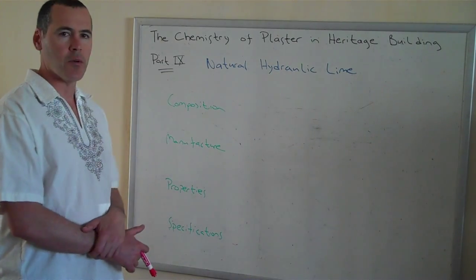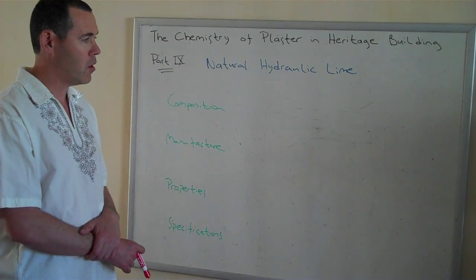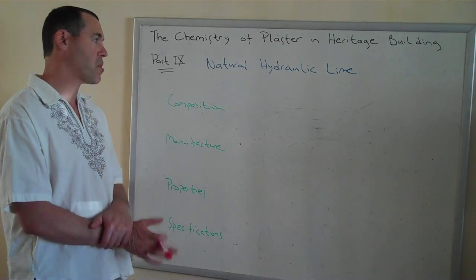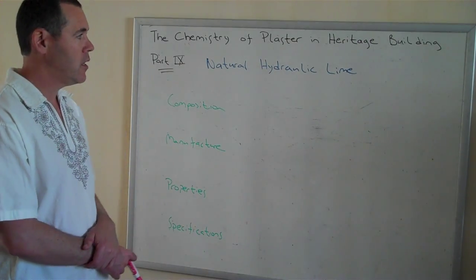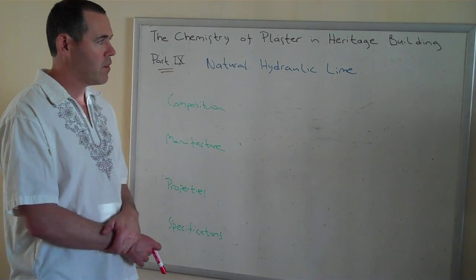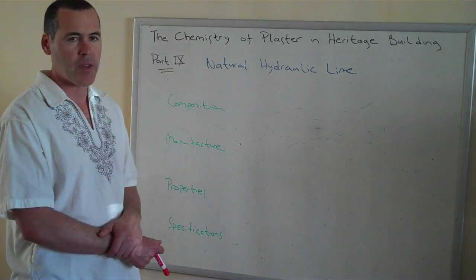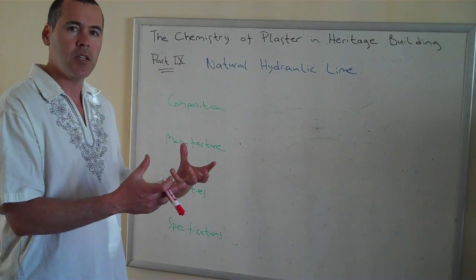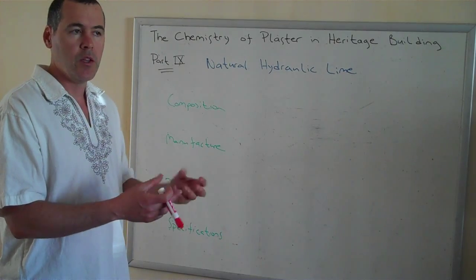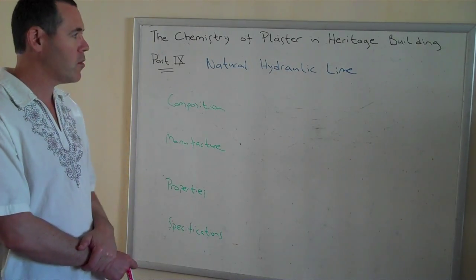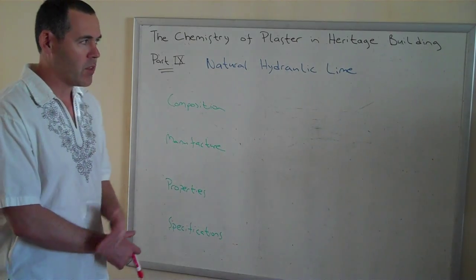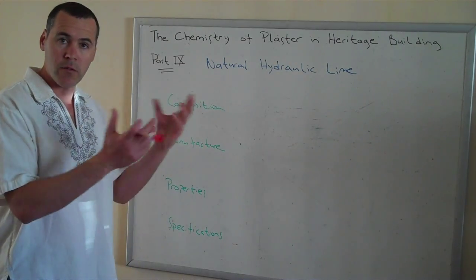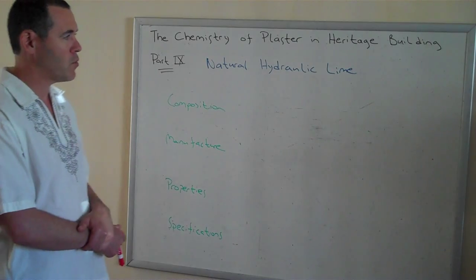Silica typically is not a very reactive product. It usually comes in the form of some sort of crystal, like quartz, which is actually what we throw into lime as an aggregate in many cases. But this silica has — sometimes due to various factors, including volcanic activity — gotten very, very hot and cooled very quickly, so it didn't really have a chance to crystallize like it normally would. In the same type of events, they might have been crushed or blown out of a volcano, very, very fine, so they precipitate as an ash.